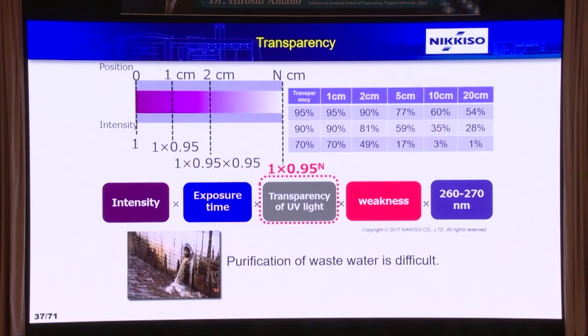And also, the transparency of the water is very important. For example, if the transparency is 95% for a 20 centimeter system, the intensity decreases to around half. But if the transparency of the water is only 70%, it's only 1%. So I should say that the purification of wastewater is very, very difficult. So we need to clean up or filter the water.